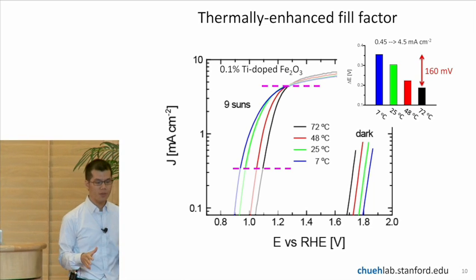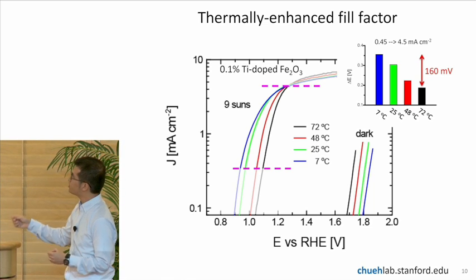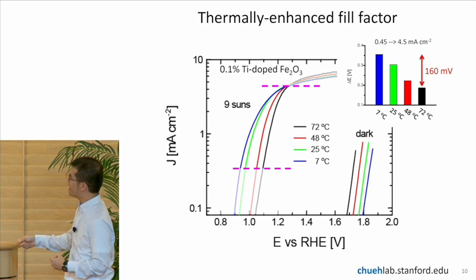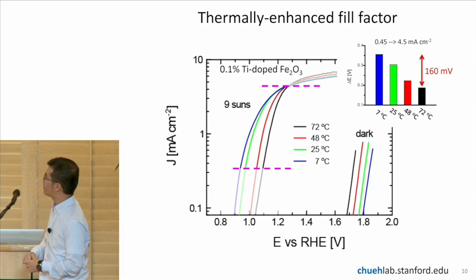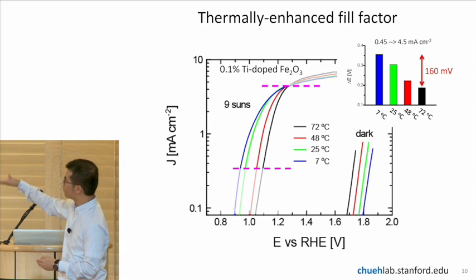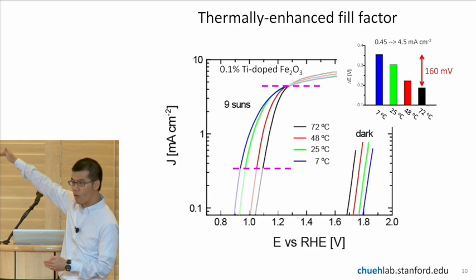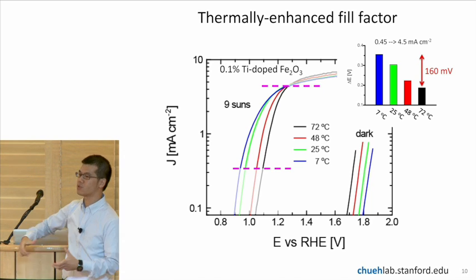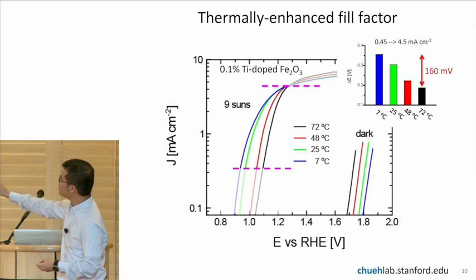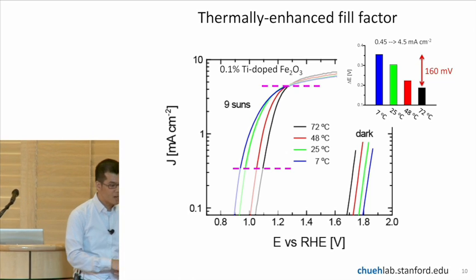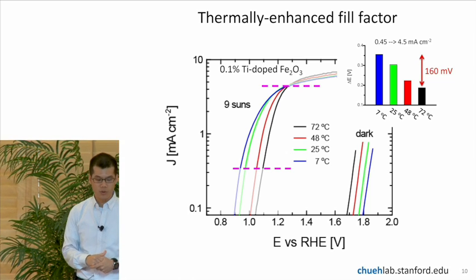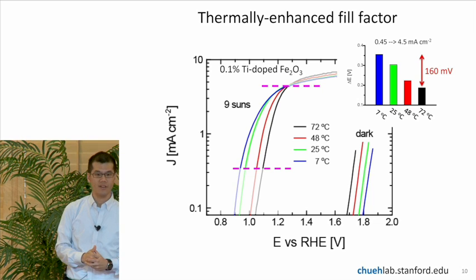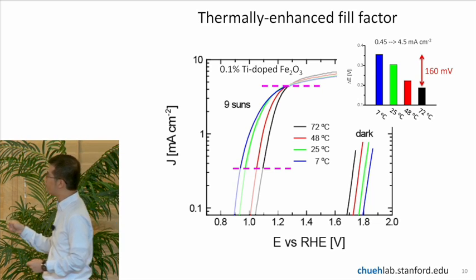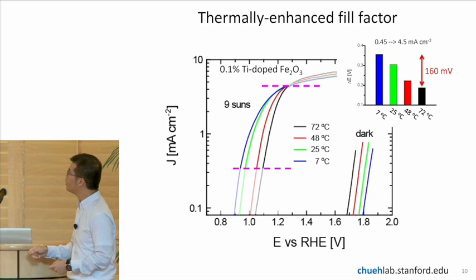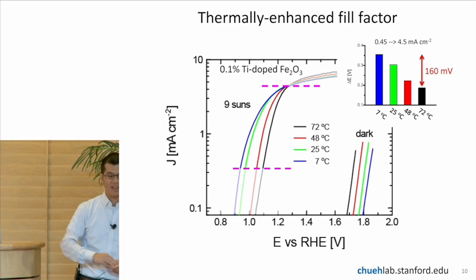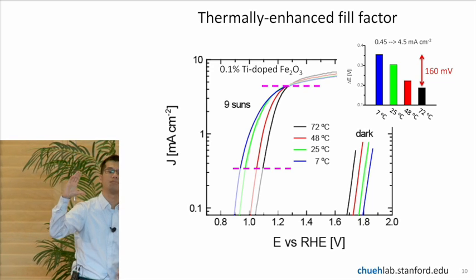I'm basically showing you here the voltage difference needed to go between these two currents. So the voltage difference needed to go from 0.4 to 4 milliamps. Okay, so this is the extra voltage needed. At 7 degrees, you need to give about 300 millivolt in order to achieve a 10-fold increase in the current. But in the case of 72 degrees C, you only need about 200 millivolt. And the difference is about 160 millivolt.